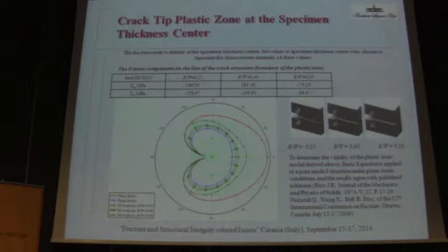And plastic zone. It can be seen that for this kind of specimen with different thickness, but in this case, stress intensity factor is assumed to be constant. So, the size of the plastic zone ahead of the crack tip is bounded by two special cases, namely plane strain and plane stress. If thickness increases, the plastic zone tends to the typical form and shape of the plastic zone for plane strain.